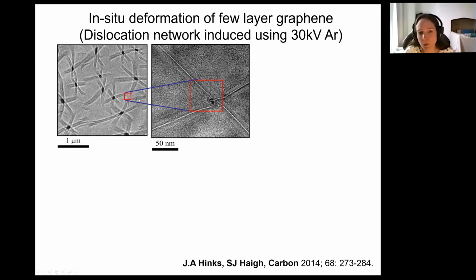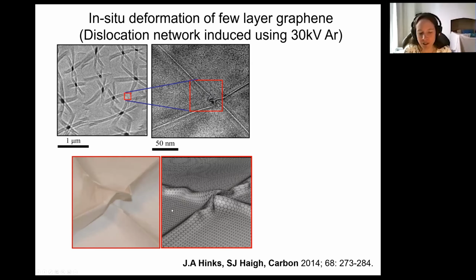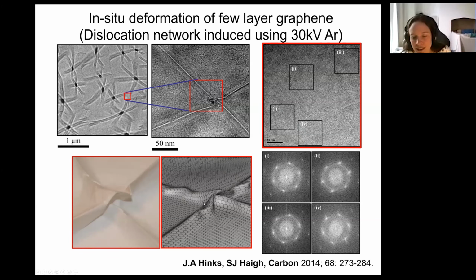So if we zoom in on one of these dislocation lines, we can see that it's a bit like having a small ripple in the sheet, and that ripple in the sheet has to overlap. So we did some simulations. This is my simulation, this is the student's simulation, but you get the general idea. The dislocation in bilayer graphene is where you have a slight ripple, and these two ripples have to then overlap and interact. And you can see that in the HRTEM.